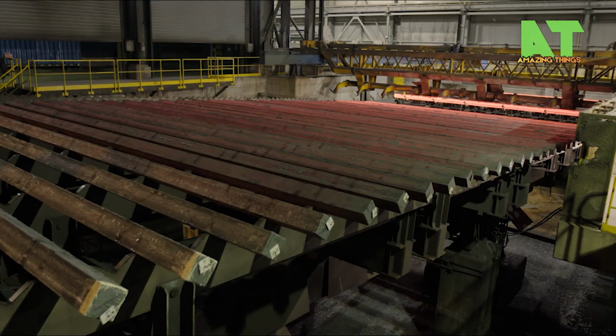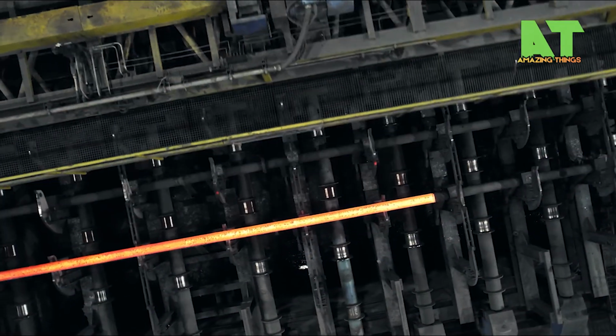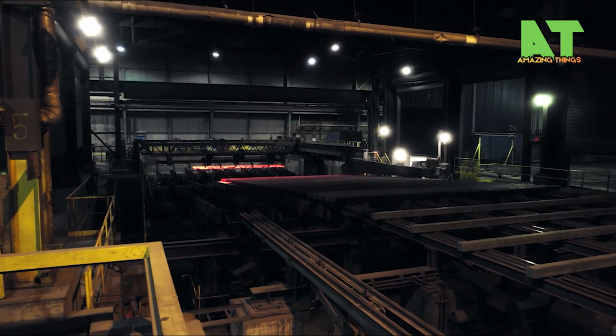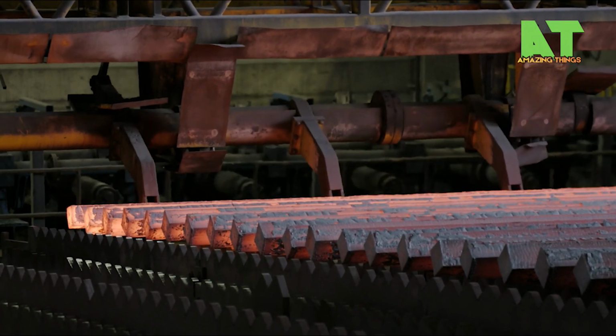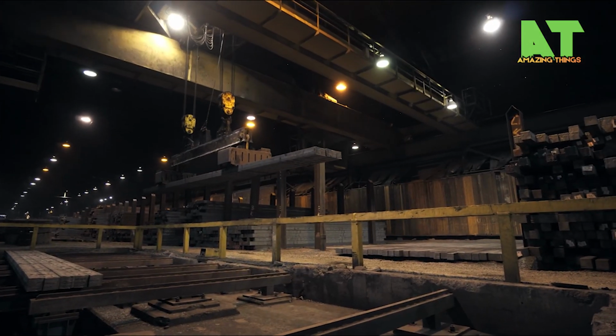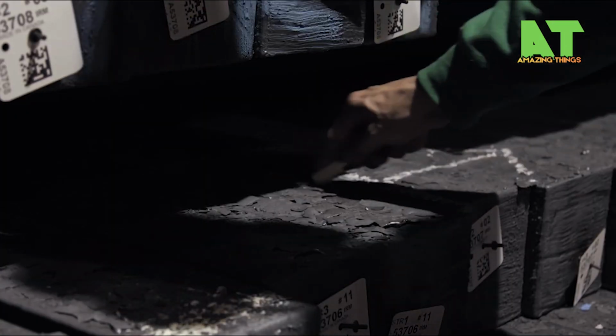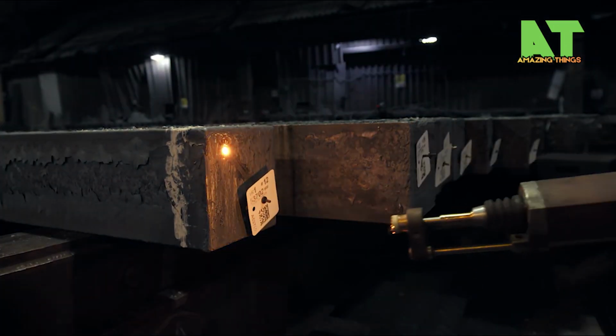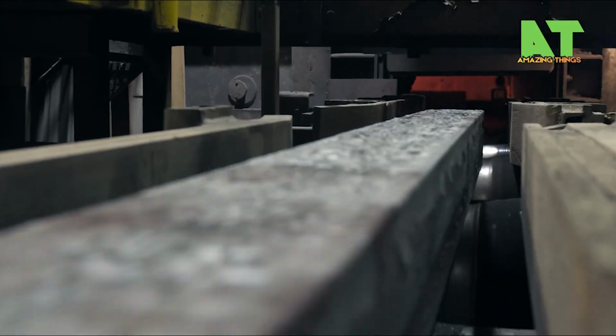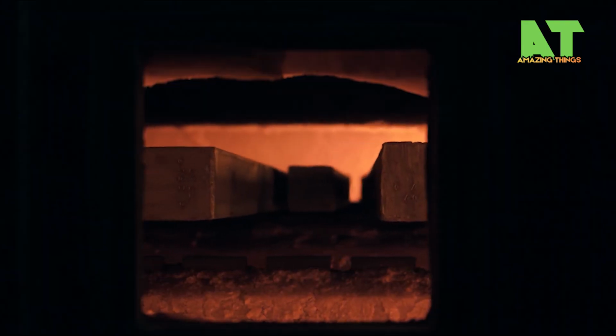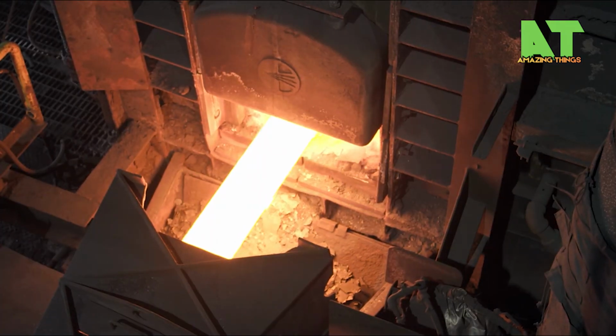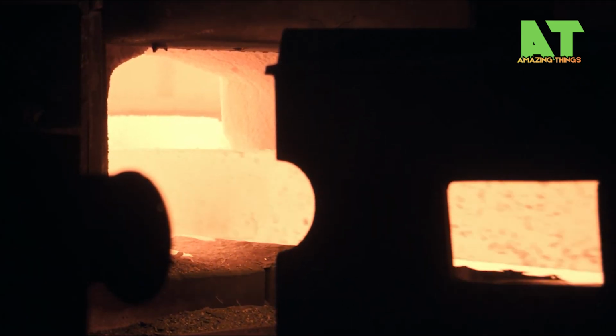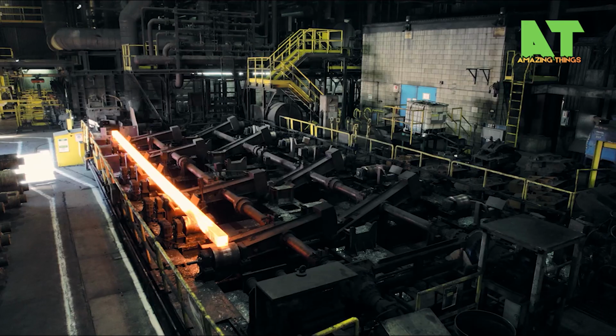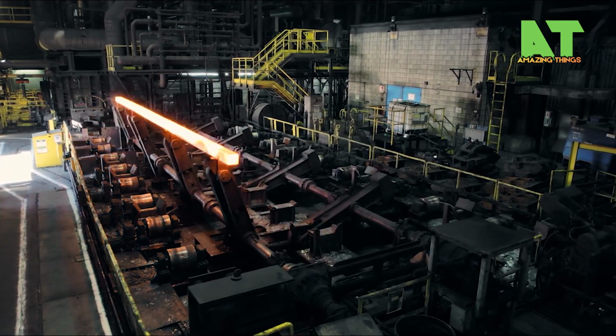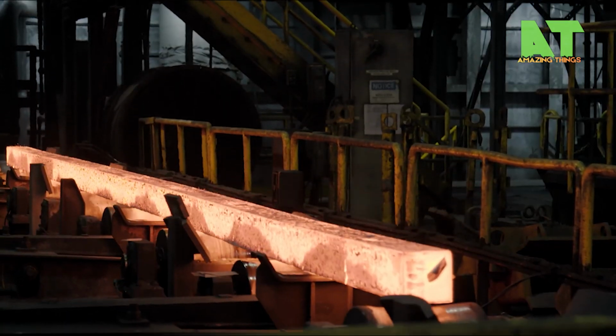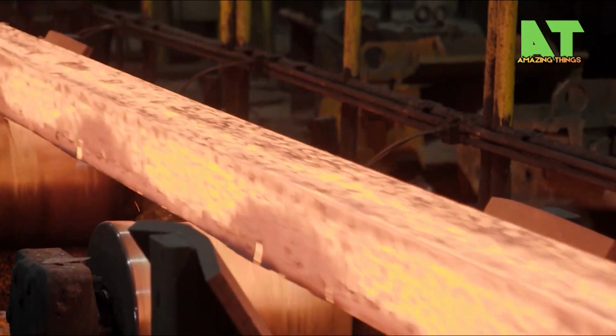We're talking about a piece of steel that starts thick and square, being transformed pass by pass into a long, round rod. The process continues through intermediate rolling stands and finally through the finishing block, a high-speed rotating assembly that delivers the wire rod at its final diameter, typically between 5.5 millimeters and 20 millimeters. At the exit, the wire rod is traveling at speeds up to 100 meters per second. That's roughly 220 miles per hour, and it's coiled by a laying head, which loops the rod into neat rings before it lands on a Stelmor conveyor for controlled air cooling.